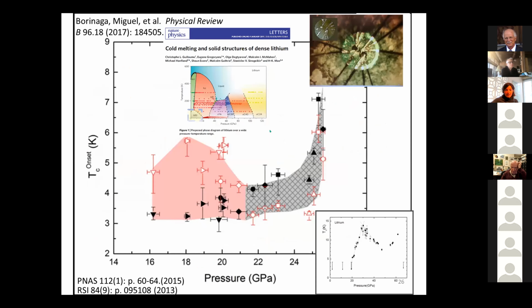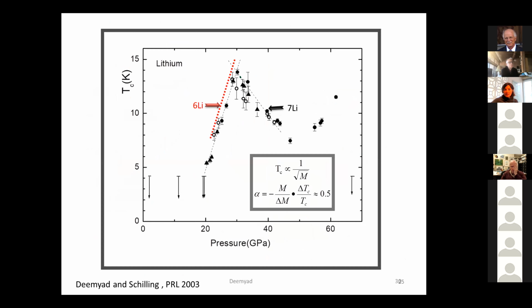superconductivity, it's a very interesting thing is that the points that you're seeing here, the black points, were taken when we pressurized, and the open circles are where we depressurized. We went to higher pressures, but for reasons we didn't know at the time, the superconductivity suddenly goes away, because it becomes a semiconductor. But then we can see that with these open circles, we could even recover. So we didn't even break the diamonds. So you can work with lithium if you keep the temperature low, if you protect the